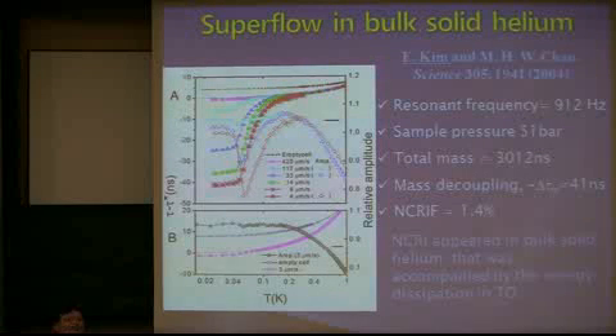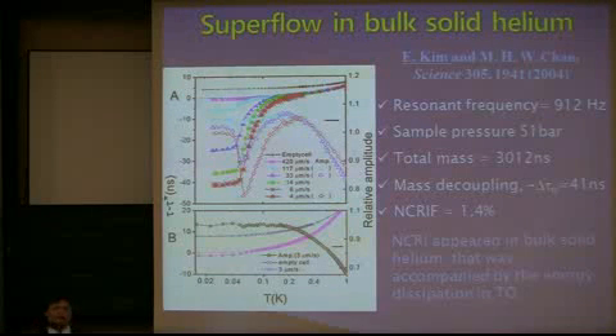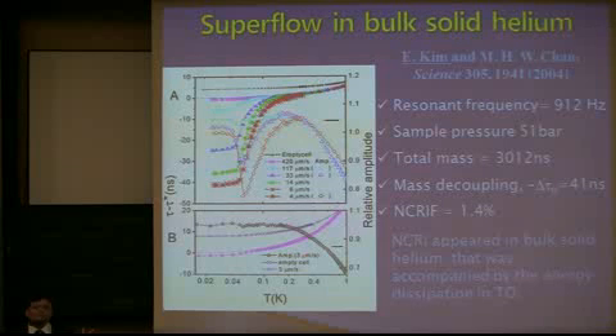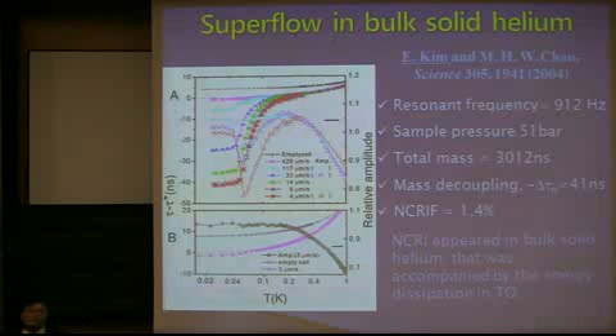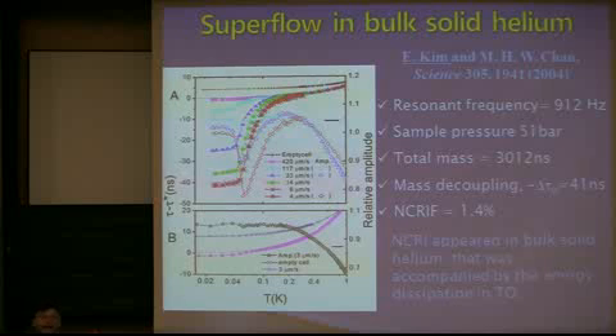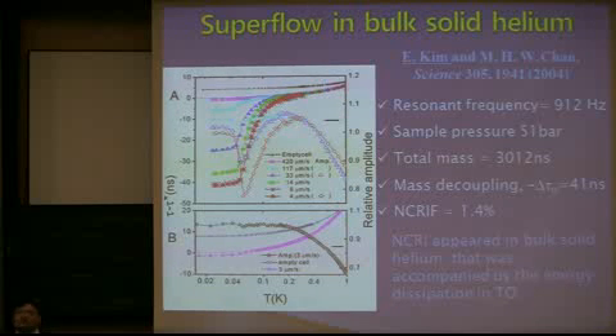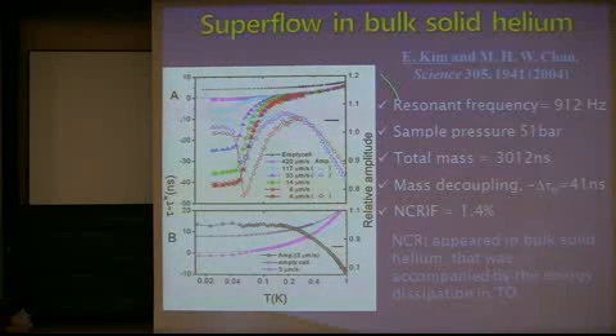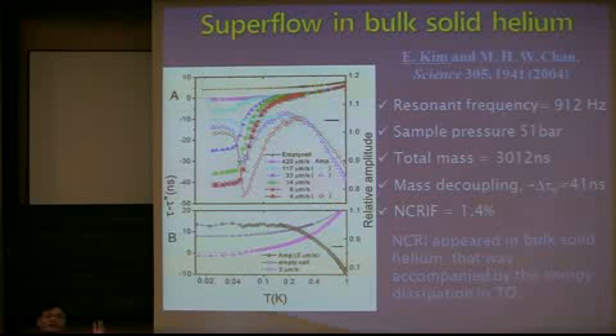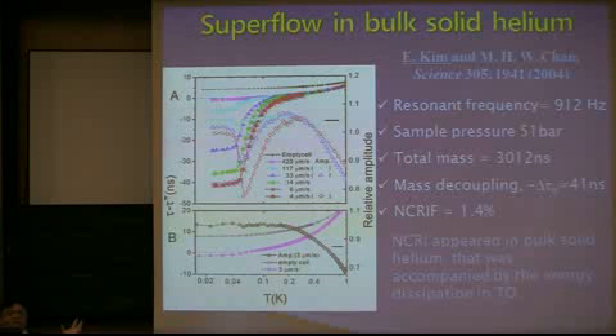So later, what we realized is that the presence of this kind of porous medium, like Vycor glass, is not relevant to the appearance of supersolid. So we did a very similar experiment. We made an annulus channel inside the torsion cell without any porous medium inside the cell, and did the measurement again.